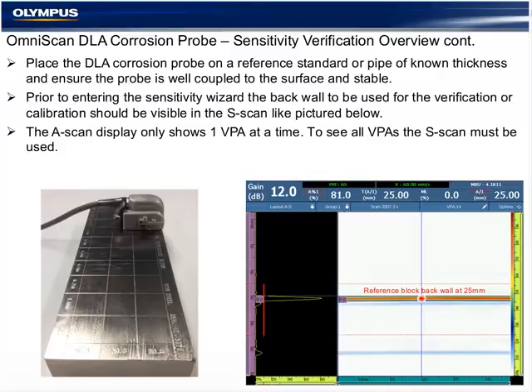The probe has a wedge that is integrated directly into the probe housing and cannot be changed. It's permanently coupled, so any loss of couplant is a result of just the water or couplant under the probe and pressure. The A-scan only shows one A-scan or VPA at a time, so be sure and focus on the entire S-scan across. Again, the blue data cursor line here in the S-scan, or tapping on the header for the VPA here, allows me to change the current A-scan that's visualized inside the probe.